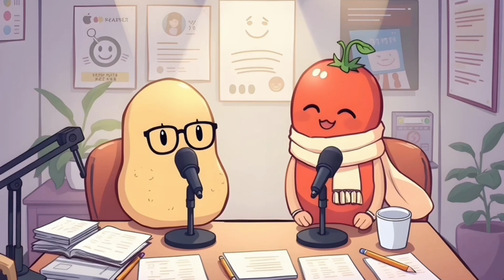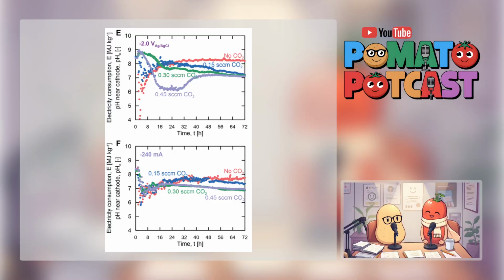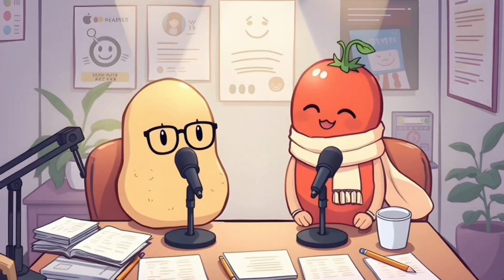Okay, back to that balance. You mentioned the CO2 making things slightly acidic locally, the electrolysis making things alkaline locally. How do they manage that interplay? It's pretty neat. The ideal setup generates just enough hydroxide at the cathode to neutralize the acidity from the dissolved CO2, react with a carbon source to make calcium carbonate, and precipitate magnesium hydroxide, all without drastically changing the overall pH of the bulk seawater flowing through. Like a localized chemical factory on the electrode surface. Exactly. And if you generate a lot of hydroxide right there, it can push the water's natural carbonate chemistry even further towards carbonate ions, which really favors making more calcium carbonate.